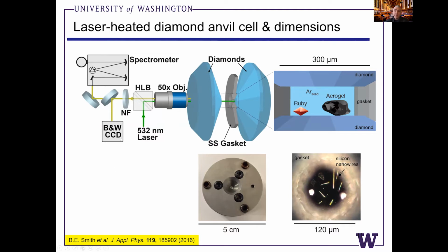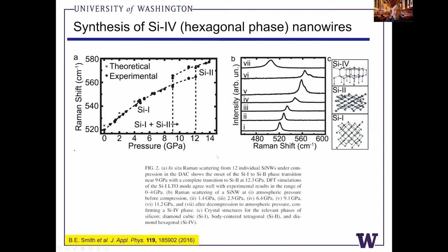So typically what we use is a laser to do both heating and also spectroscopy. I'll return to this momentarily in a few slides. We also use ruby crystals. These are chromium doped alumina grains, effectively just ruby shards, that we can look at the chromium crystal field splitting and measure the pressure in the diamond anvil cell. So we can measure the pressure from the ruby, and we use optical emission from the carbon aerogel while it's being laser heated, basically the Planck emission, the black body spectrum, to get the temperature. And I'll talk a little bit more about that in a few slides.